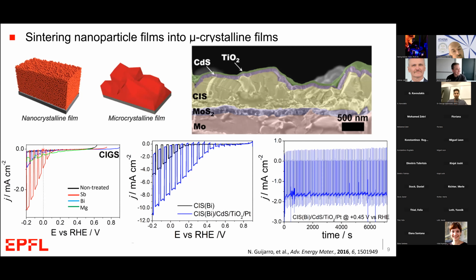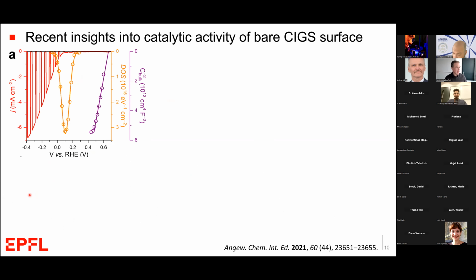So back in 2016, we were quite excited about this result, but actually something more interesting popped out to our attention, which was that even these films without any of these fancy overlayers, without the TiO2, without the CdS or the platinum, they already showed some activity for the water reduction reaction here shown in this red curve. And that has inspired more recent work where we've studied the surface of these bare films to try to understand what site is actually catalytically active for that water reduction reaction. If we can figure that out, perhaps we can eventually use these nanoparticles also one day in photocatalyst type systems.